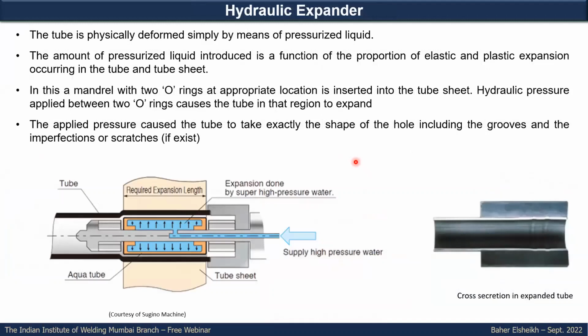The hydraulic expansion is applied by applying hydraulic pressure in a tool inserted in the tube sheet hole area, and by applying the pressure you will force the tube to seal against the tube sheet hole. As we said, this application might be applied without grooves in some cases or with grooves. And in the hydraulic expansion, the uniform application of the pressure will force the tube to take exactly the shape, so if you have a groove, it will take exactly the shape of the groove.